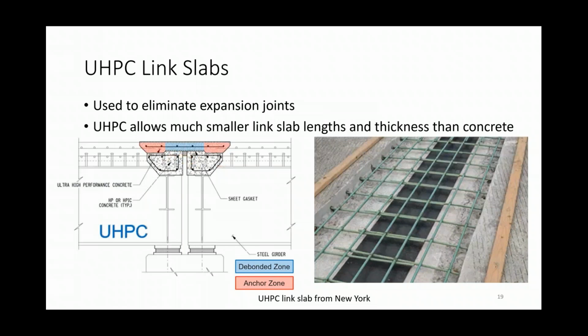So New York has started replacing some bridge decks with expansion joints with these link slabs, and they reported that they've had great performance with these. So essentially, when they switch to UHPC, they now can have a link slab that's much shorter, so just a couple of feet, you can see on the right-hand side. And the thickness is also smaller too. So that completely eliminates the expansion joints, and that's how they get durability. So it's essentially acting like a hinge on top. That's why they debond between that UHPC layer and the girders.